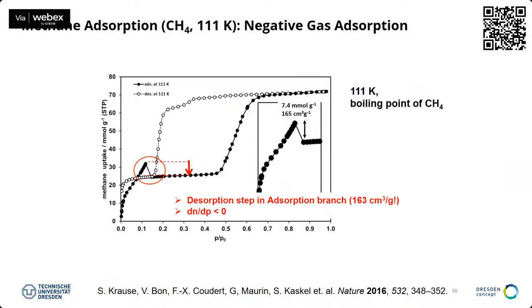But this negative step was very counterintuitive. It was more than 165 cubic centimeters per gram, 7 millimole per gram. So this means that the material pushes out gas, basically, while you are increasing the pressure. And this was very counterintuitive at that time, because from thermodynamics, it's forbidden, actually. When you increase the pressure, you should always take up more gas. You should not push it out. That's totally counterintuitive.